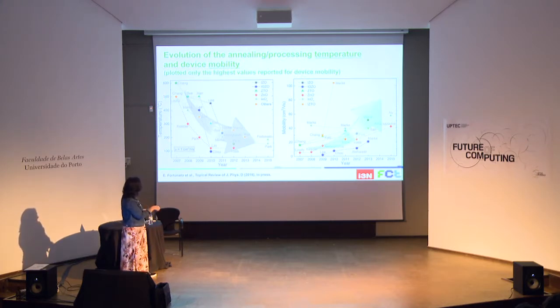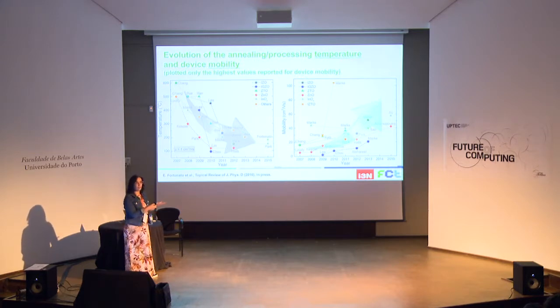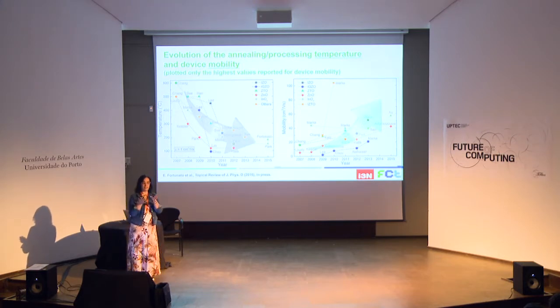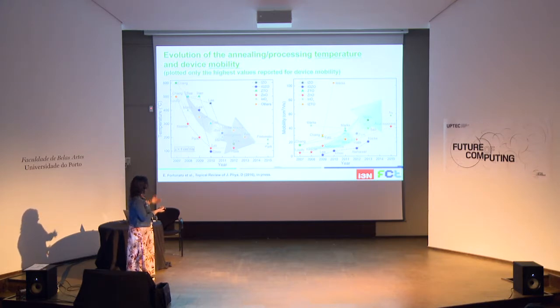I plot the temperature over the years, and what we have observed is a drastically reduced value of the temperature. For example, the previous results needed to heat the materials up to 600 degrees, which is not compatible with the use of a plastic substrate. But nowadays, we are able to produce these devices at temperatures around 150 degrees, and in some cases even lower, 100 degrees. We are able to promote all these reactions because instead of using only temperature, we can add, for example, UV radiation, adding other sources of energy to the system in order to promote all these chemical reactions and at the end achieve the same result.